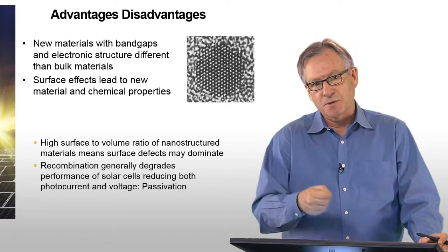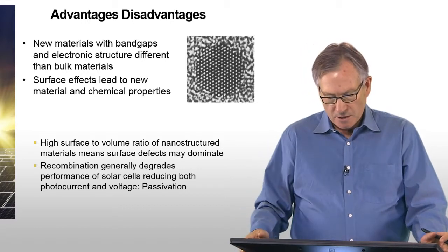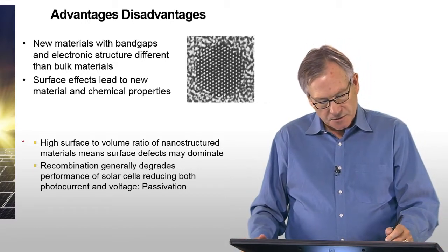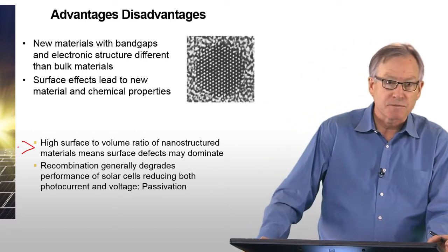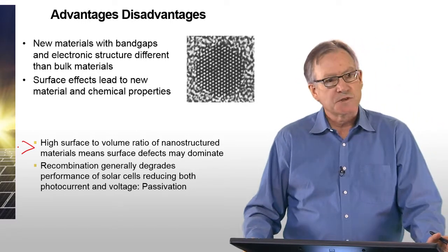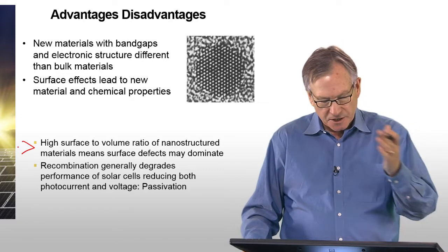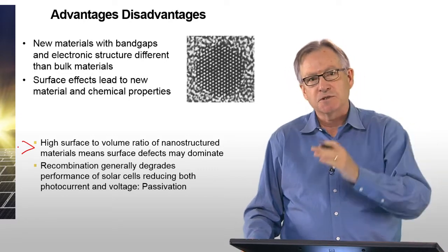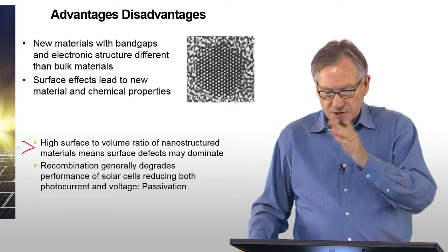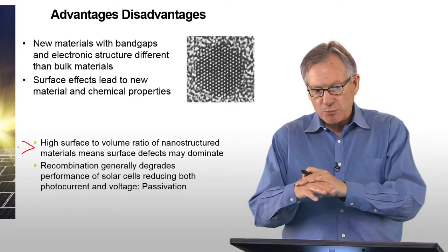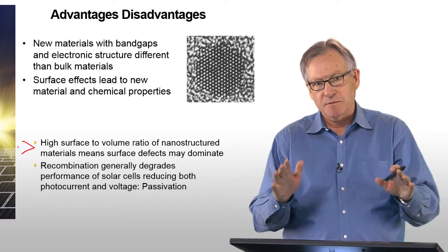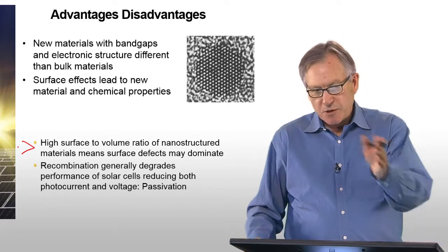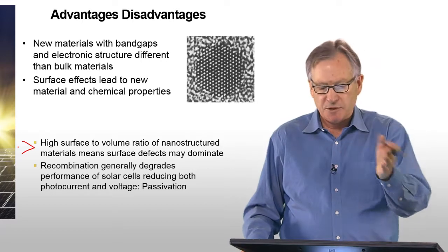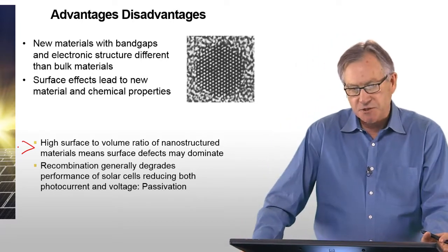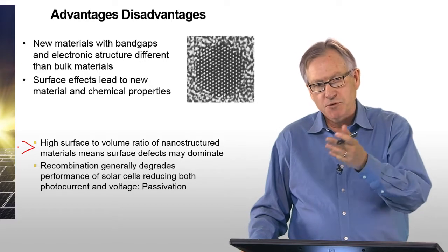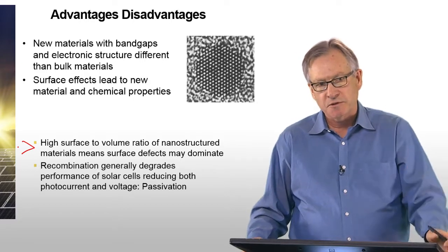One is reducing the open circuit voltage and the short circuit current, and hence the power. So the problem then in nanostructures is that they have a high surface to volume ratio, and therefore that means that surfaces can dominate, and dominate in a negative way. And so therefore passivation, which is the process of basically mitigating the effect of these dangling bonds and broken bonds on the surface, tying them up with some other material like organic material or an oxide. Passivation plays a much more important role in terms of using nanotechnology in solar cells than in other technologies.